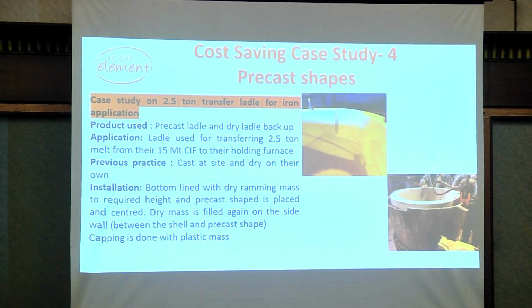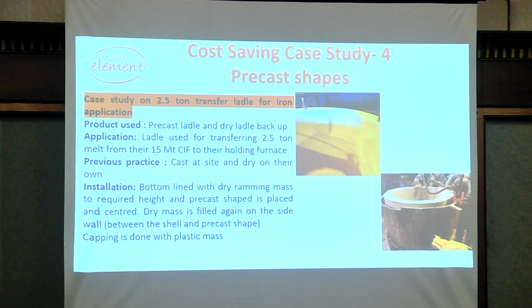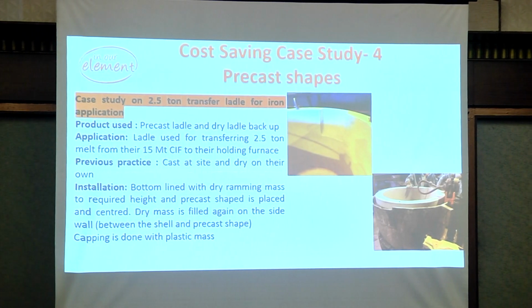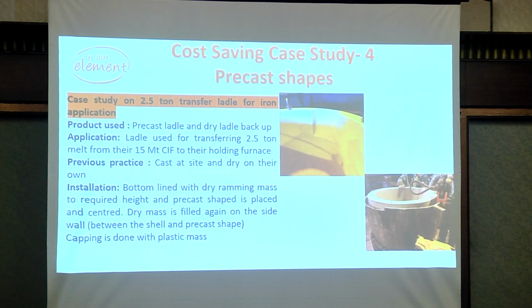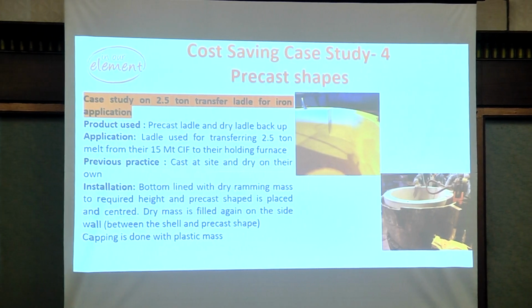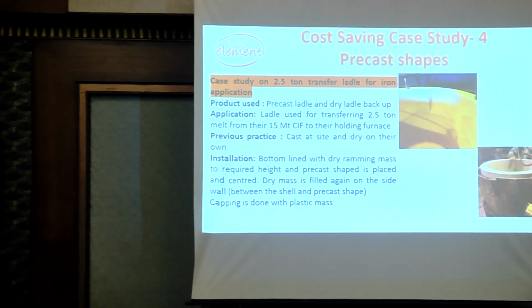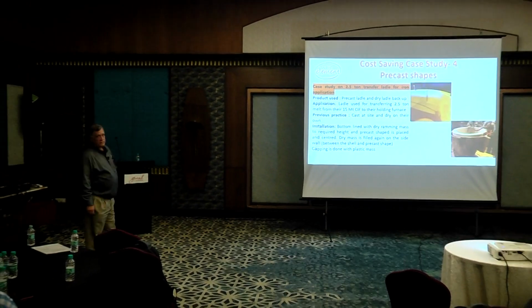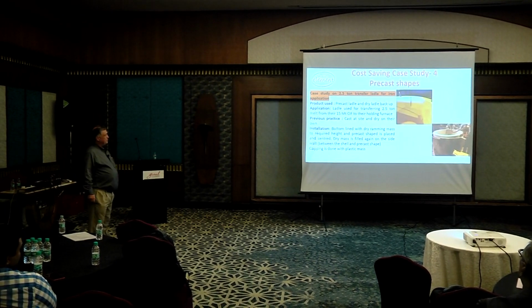So again, cost savings, study 4. 2.5 ton transfer ladle. Product used is a precast ladle with a dry backup. So the application is a ladle used for transferring 2.5 tons of metal from a 15 metric ton coreless furnace to a holding furnace. Installation, bottom lined with dry ramming mass. First you put in the dry, level it, set it, fill it again with dry, and then cap it off typically with a wet ram or a plastic.